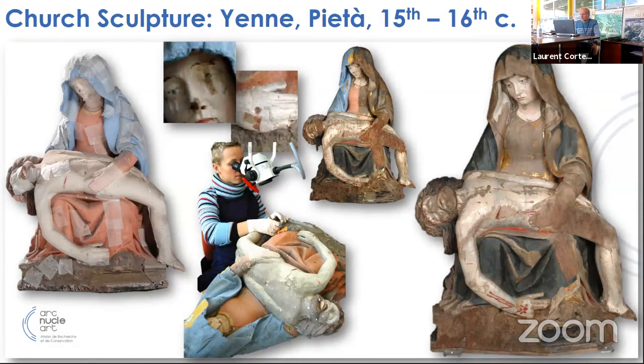Another example is this nice restoration also of a previously badly recovered sculpture with unskillful plaster repair. You can see on the hand of the Mary. And so after a study of polychromies, the exogenous material, plaster, were removed, and the recent different paint layers were removed until reaching the original layer. Even if we knew that in this case it was very incomplete, but I hope you can see the difference in before and after, and you can see that the quality of the painting and the quality of the sculpture is very nice after restoration.